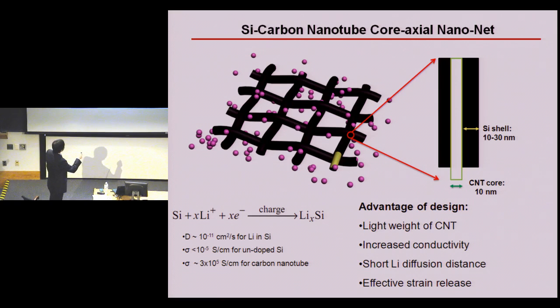So I will show you the design of this structure, a core-shell structure. Here, I have a carbon nanotube conductive framework, or mechanical backbone, and overcoated on the carbon nanotubes is silicon. In this case, carbon nanotubes will function as excellent channels for electron transport. And meanwhile, carbon nanotubes are also mechanically stable, so they will hold the entire structure during the lithiation process. And meanwhile, this kind of porous structure, as I said in the beginning, will decrease the diffusion length for the lithium into the silicon structure, which will enhance the power performance.